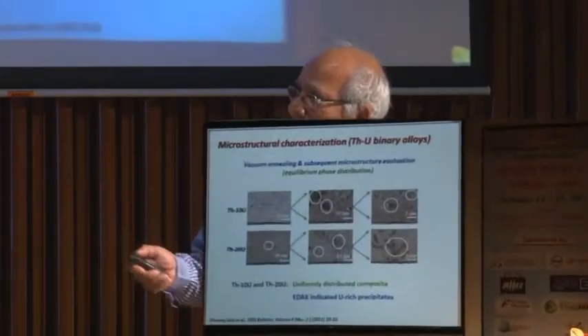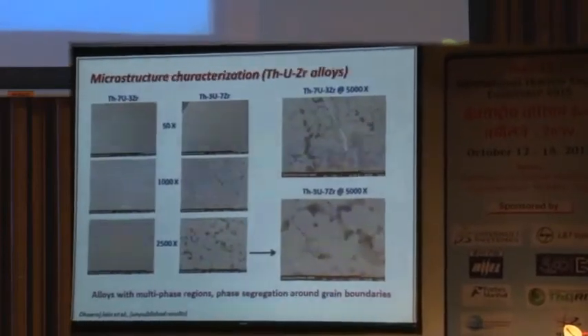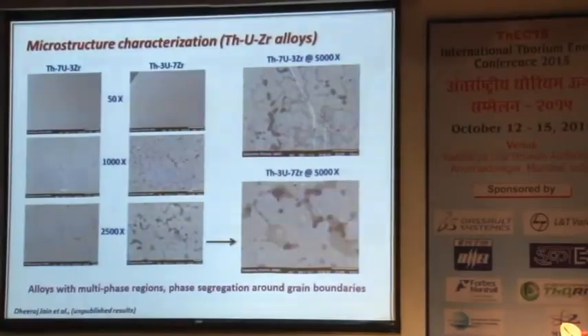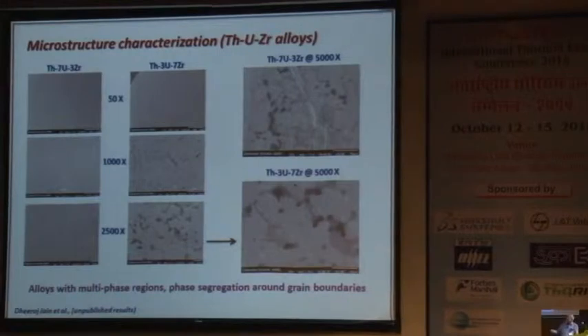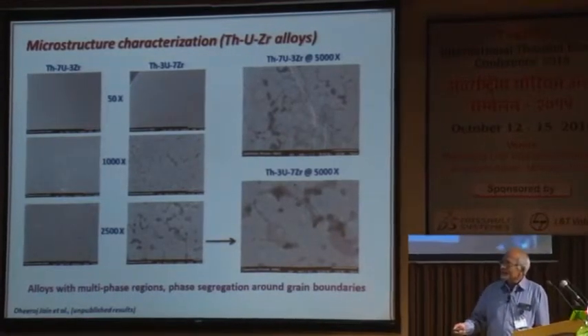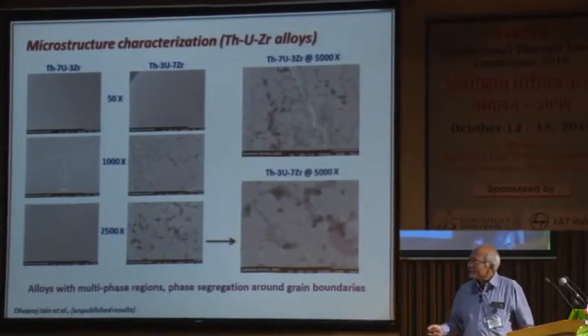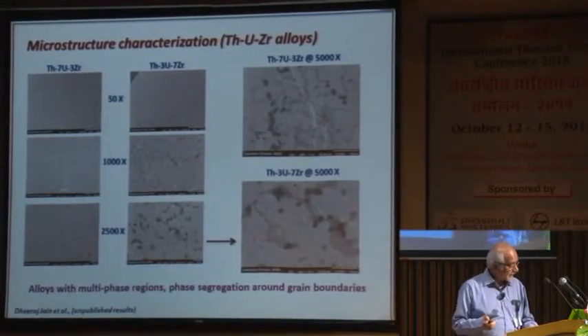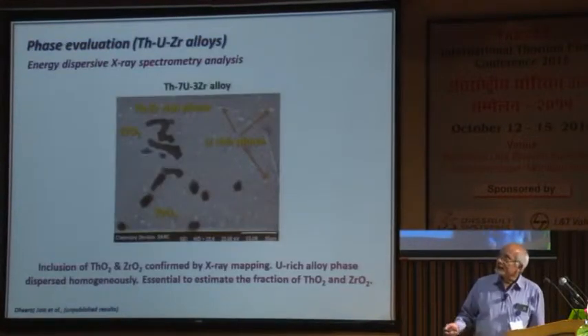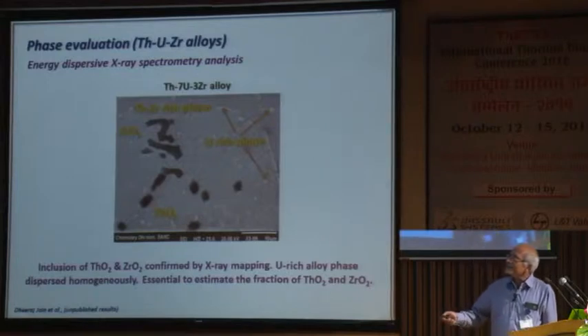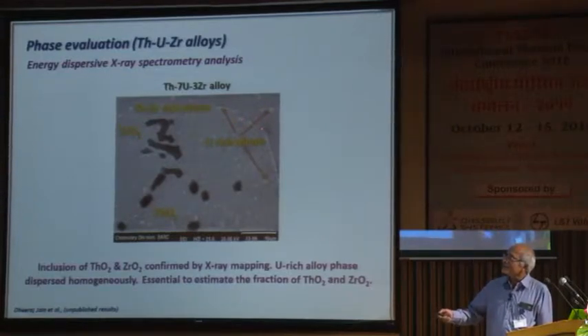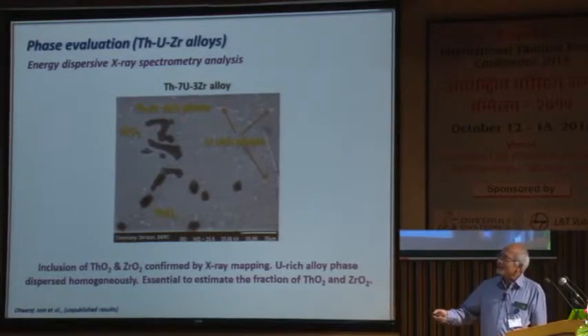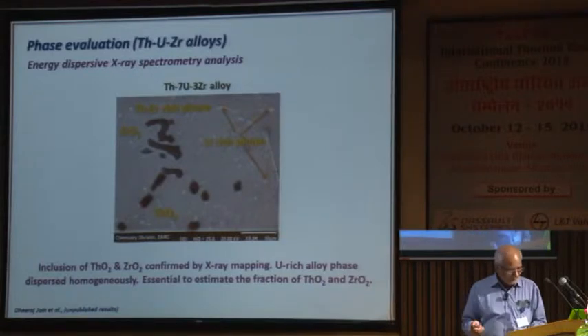That is, EDAX indicated the uranium-rich precipitates in the prepared alloy, and this is the further work on uranium, thorium, zirconium alloys. You can see that alloys with multi-phase regions show phase segregation around the grain boundaries. You can see it very clearly here. These are the uranium-rich phases, which are the gray spots here. This is generally the thoria-zirconium-rich phase, and this is zirconium oxide and thorium oxide.